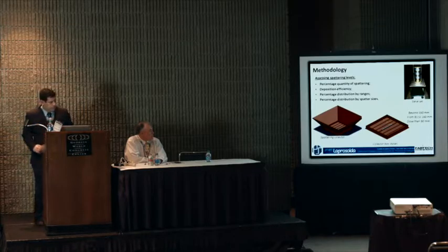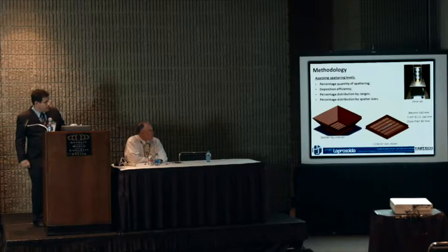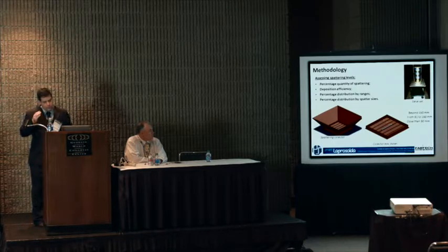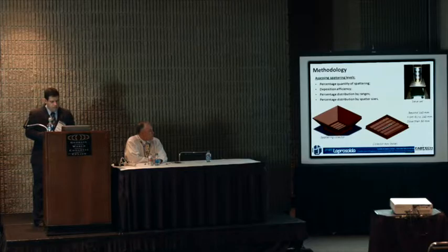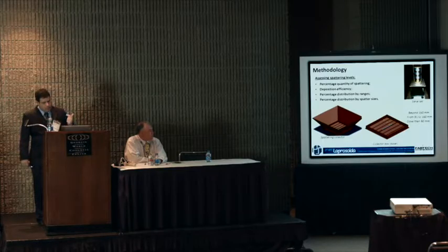So that's a small box just for collecting. We weld within this box, and after we use a sieve to collect the different sizes of the spattering, and we can measure both the percentage of the spattering and the deposition efficiency by weighing the welded bar before and after the weld. We have the percentage distribution by range of the size of the spatter and the size of the spatter itself.